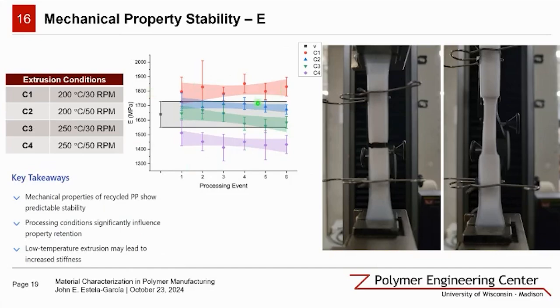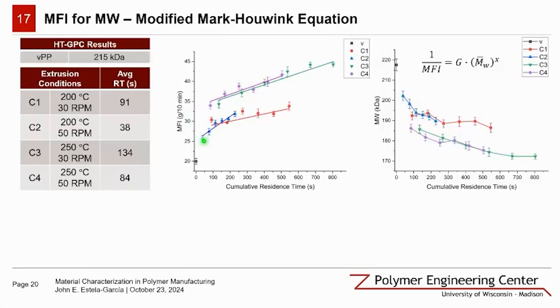So these results suggest that with careful control of processing conditions, we can maintain consistent mechanical performance in recycled polypropylene specifically. The stability in mechanical properties is a key factor in promoting the use of recycled materials in high performance application. This is providing manufacturers with the confidence to incorporate higher percentages of recycled content without compromising product integrity, focusing more so on the conditions that you're processing your material at.